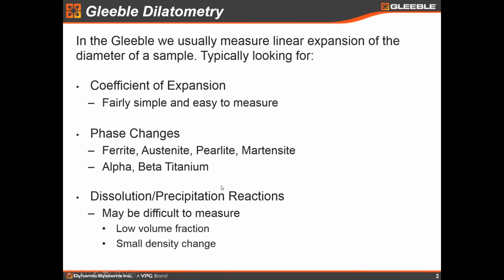The third primary thing that people use dilatometry in metallurgical research for is dissolution and precipitation reactions. Now, these are actually often quite difficult to measure. The precipitate in a metallic material is usually a very low volume fraction of the entire material. Therefore, even if you have a reasonable density change from a solid solution material to a precipitated material within a metallic sample, if you only have 2, 3, 4% volume fraction of that precipitate, it can be very difficult to measure using dilatometry. And often the products of precipitation have a relatively small density change from the solid solution. So combining these two together means that it can be quite difficult sometimes to measure dissolution and precipitation reactions, but not always impossible. So just something to keep in mind.